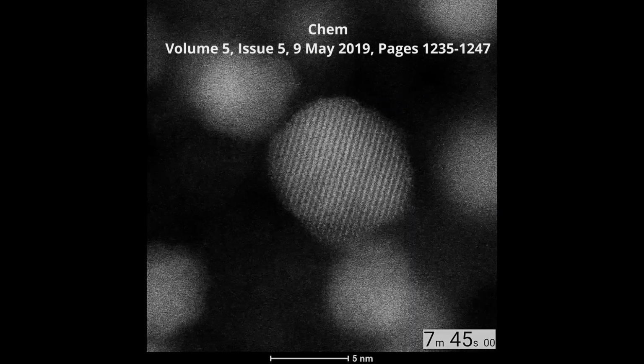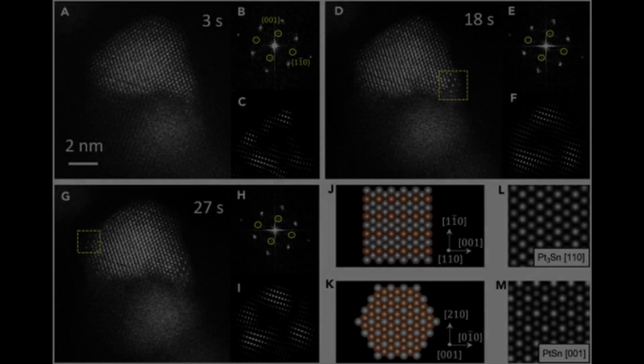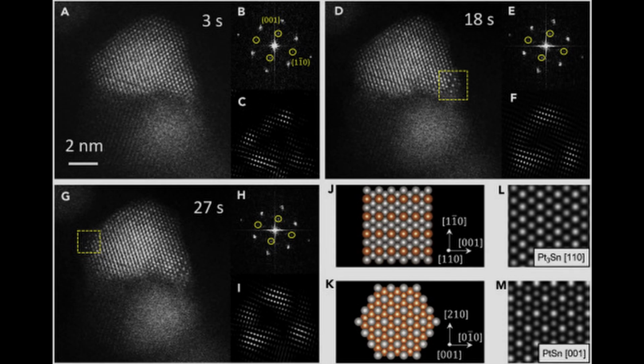The reducibility of tin oxide depends largely on the interaction with the support. Strong interaction makes the reduction more difficult. However, platinum is in close contact and assists with the reduction of tin oxide. From the geometrical point of view, it can be suggested that isomerization, hydrogenolysis, and the formation of coke precursors can all be suppressed by reducing the size of platinum nanoparticles.